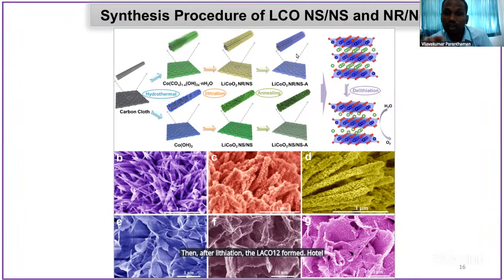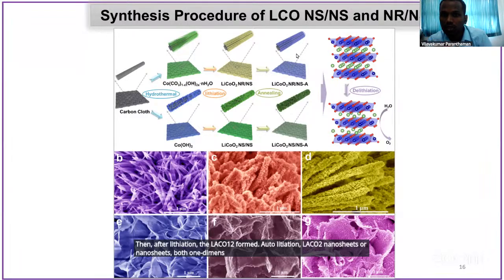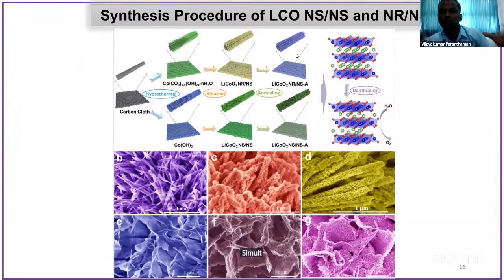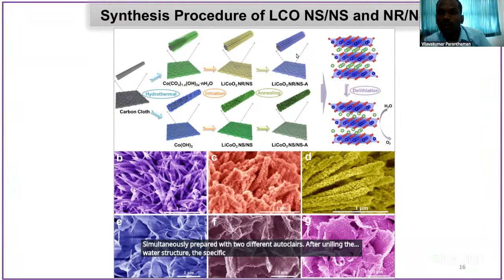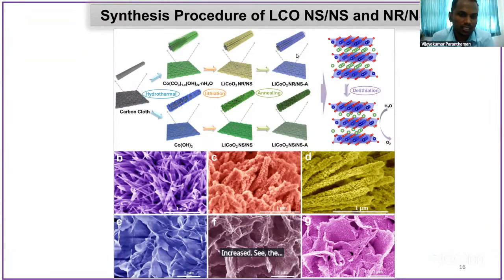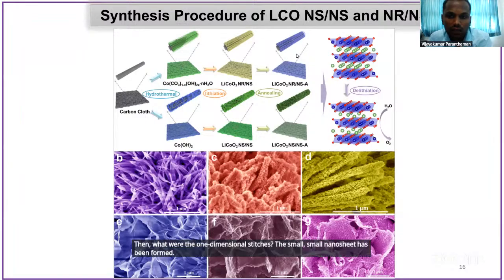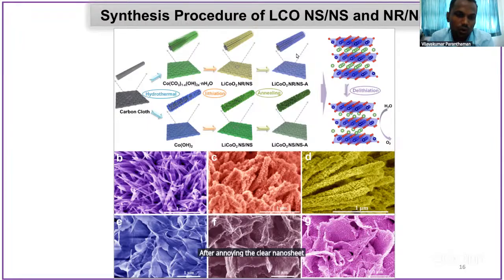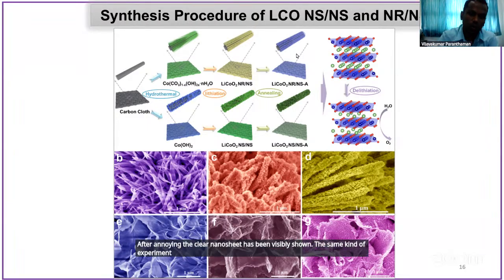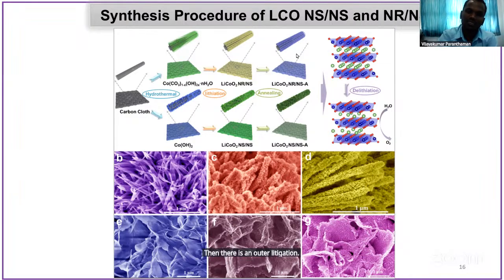After lithiation, LiCoO2 nanosheets on nanorods and nanosheets on nanosheets, both one-dimensional and two-dimensional, were simultaneously prepared with two different autoclaves. After annealing, the porous structure and the specific surface area have increased. See the surface morphology. First the one-dimensional structure, then over it small nanosheets have formed. After annealing, the clear nanosheets are visibly shown. In the same kind of experiment, first the nanosheet grows, then after lithiation the nanosheet gets thicker compared to after annealing. Then after annealing, small nanosheets and pores are formed clearly. We can see this through the SEM surface morphology.